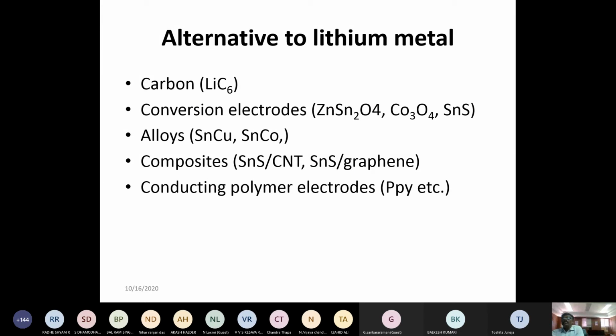That's what we are using in our lithium ion batteries now. And the other system is called conversion electrodes. So examples are SnS, Co3O4 and all. And alloys can also be used, and composites like CNT, SnS, and graphene can be used. But in 1999, 2000, even in the early 2000s, the conducting polymer electrodes, for example, polypyrrole, polyaniline were used as electrodes. But those conducting polymers are highly unstable in the non-aqueous electrolytes because they degrade very fast. They lose their molecular weight.